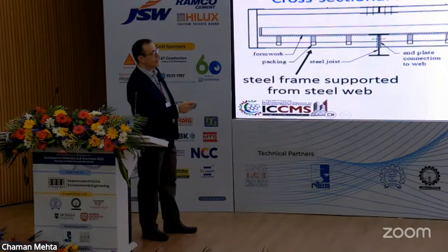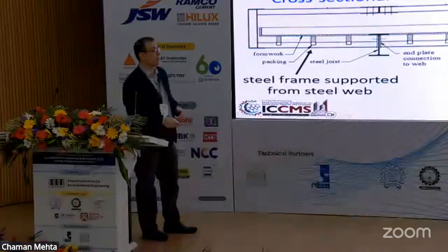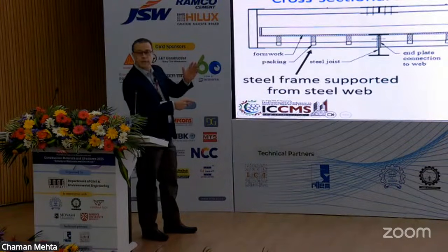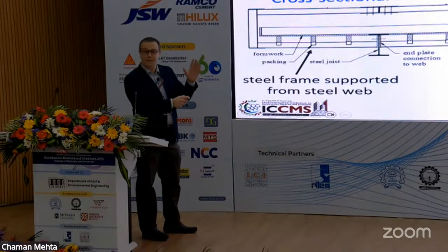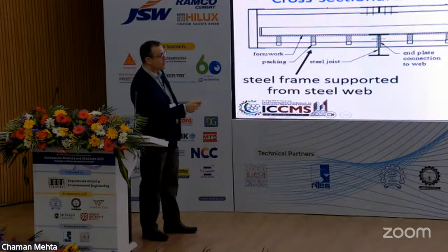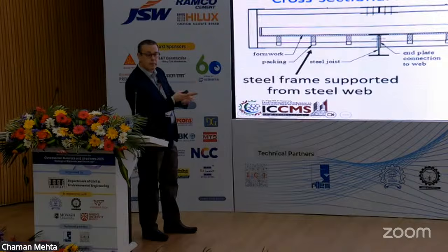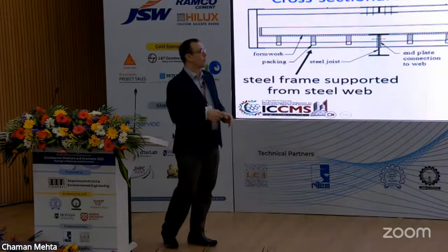So in this case, for example, we set up this simple frame system to create a scenario where we cast and prop. This frame is attached to the web. We put the formwork on top of it, we cast it, and then we remove the elements. We did simple things, I would say it's common sense. Sometimes good structural engineering is about common sense. To load and unload them, we just release some shims, and it worked perfectly well.